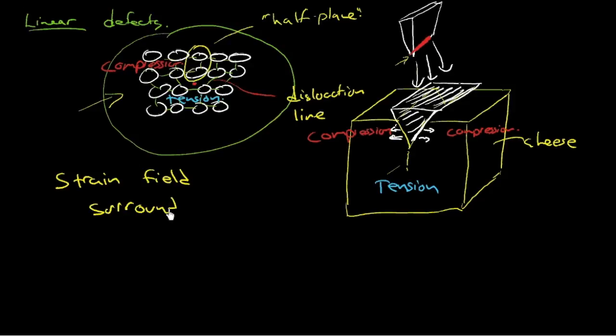And that's actually stored strain energy. It's elastic energy, if you like to think of it that way. It's elastic energy stored in the lattice in the form of these disturbances from equilibrium spacing. These atoms, if we modeled them, I drew them with these little green lines. But if you imagine them with little springs, well, these are being compressed and pulled in tension away from their equilibrium spacing. And that's energy stored as strain energy.